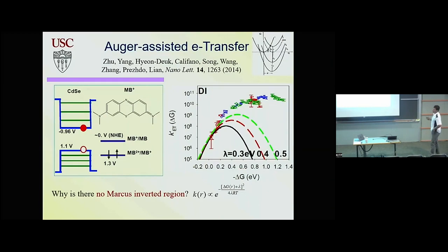What it's about is a very simple model that's used to talk about transport or charge transfer in an incoherent regime. You have an initial state and a final state, and you have a barrier that you have to cross. If your final state drops in energy, the barrier becomes smaller and smaller. At some point there's no barrier, and this is when the rate is the highest. But if the energy of your final state is too low, you start crossing on the opposite end, and then the barrier shows up and the rate decreases again. This is the Marcus inverted regime. Tim Lian was trying to observe this in this system where you have a quantum dot and a molecule, and instead of getting the inverted regime, he got saturation.